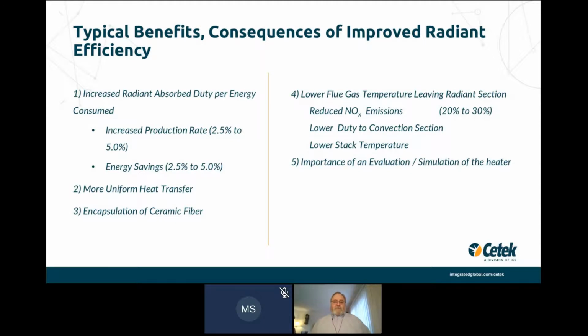So the typical benefits and consequences of improved radiant heat transfer. We get an increased radiant absorbed duty for the amount of energy that's consumed, efficiency. So we can use that improvement in efficiency for increasing the production rate without increasing firing, or we can save energy. We can save the fuel consumed for producing the same amount of product. We get a much more uniform heat transfer. And in a ceramic fiber lined unit, the coatings are much more durable than the friable ceramic fiber surface. So we encapsulate the ceramic fiber, and there's no loss of the fiber downstream to the convection section or SCR units if you have them.